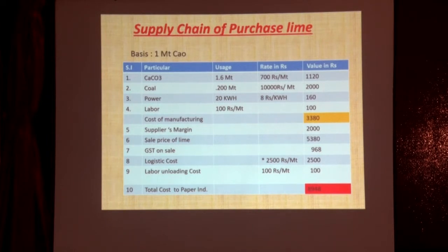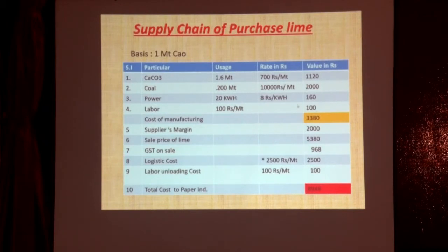Producing lime has two processes. One is a slow process and one is fast. Our rotary lime kiln process has fast cooking. Once they feed all the material, coal and limestone, they leave it for 3 days. Slowly it cooks. So the coal requirement, not theoretical, the practical coal requirement, I already told you the coal requirement is 153, but practically the energy requirement is 4.22, 4.5 gigajoule per ton of CaO.